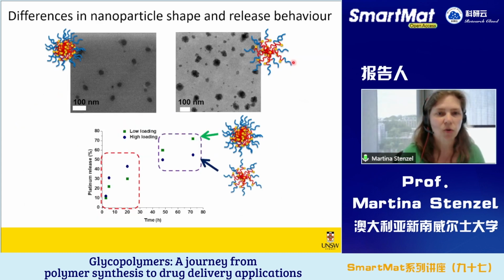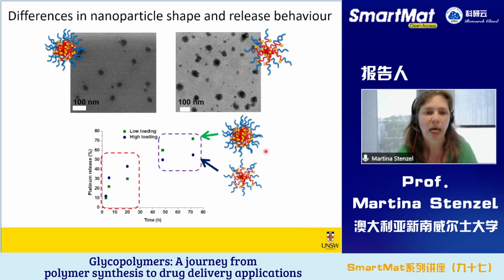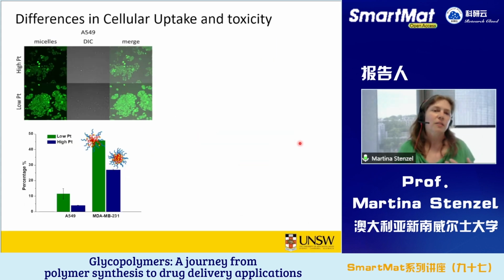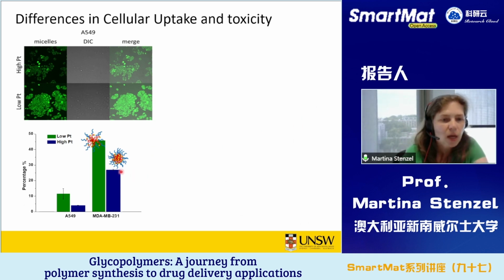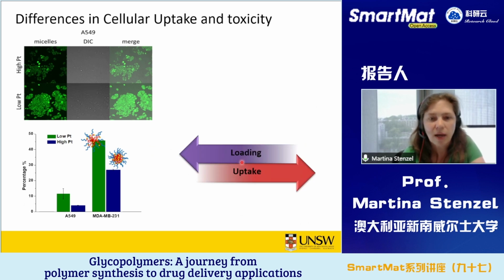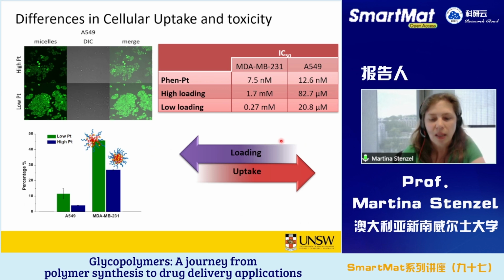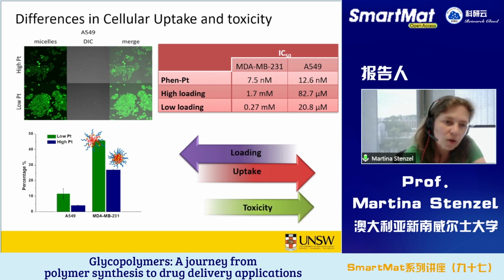At first, we characterized our nanoparticles, and actually the low-loading particle was even a little bit bigger. It was a little bit less well-defined, while the high-loading ones were nicer nanoparticles. The drug release was quite similar, but what was really surprising was the difference in cellular uptake. As I said, the high-loading one should be much more efficient. However, what we found was that the uptake of the low-loading nanoparticles was much better. So the cell really preferred these very ill-defined nanoparticles compared to the other ones. As a result, we also found a much higher toxicity. The low-loading nanoparticles were much more toxic than the high-loading particles.